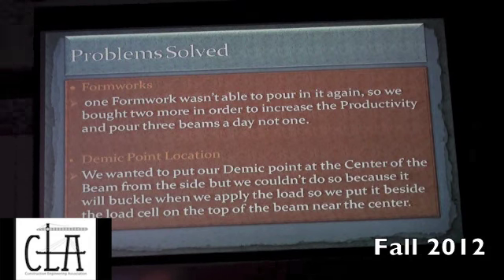The formworks: one of the formworks was not able to pour in, so we bought 2 more new formworks, so we could pour 3 beams at the same time and increase our productivity. The Demec point: we wanted to fix our Demec point on the front side of the beam from its center, but we did not do that since once we apply load, it's gonna buckle, so we inserted it on the top side of the beam beside the point load.